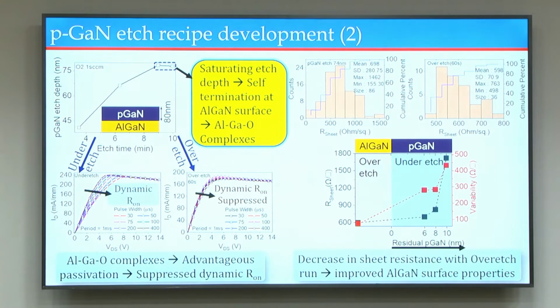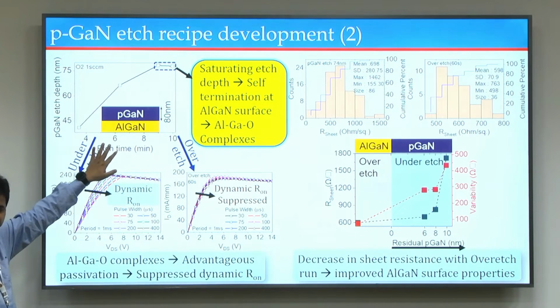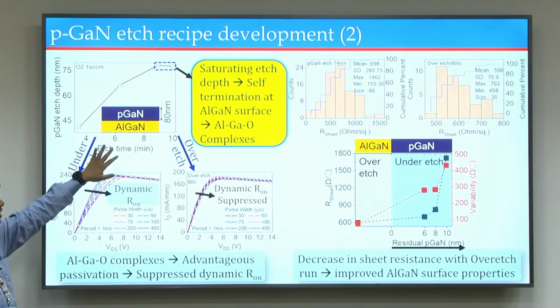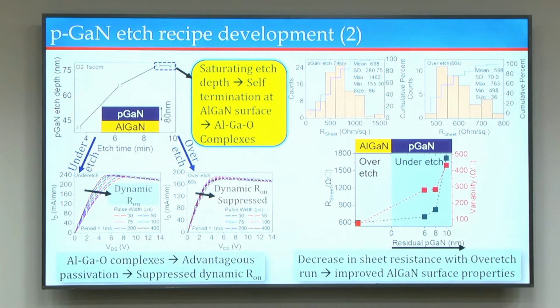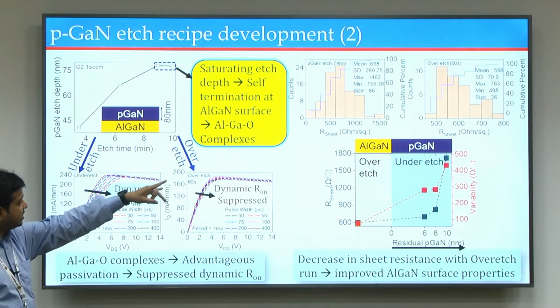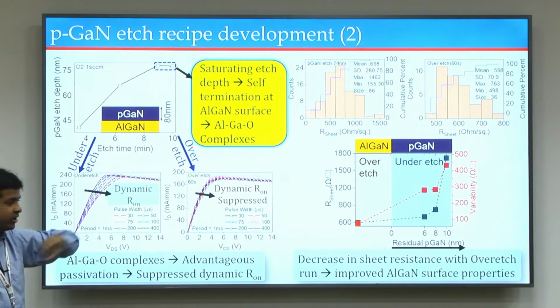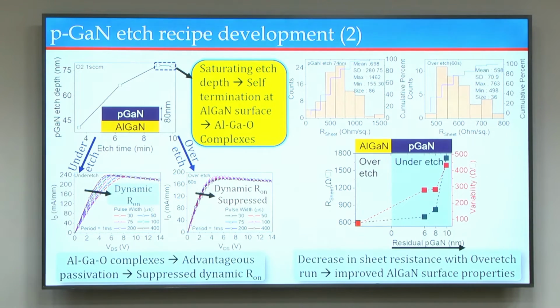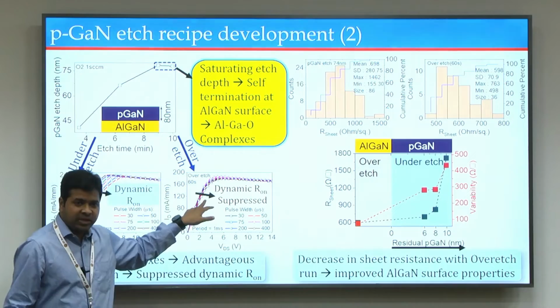So you need a chemistry like this, which I can tell you required a lot of runs and optimizations to get to this point, and once you have that, then you can completely remove pGaN from wherever you don't want it without having any variability like issues. Now I was talking about if you don't optimize this well, you may end up having serious variability issues in terms of sheet resistance and contact resistance. And the other way is that you may under etch, right. Okay, let's not etch completely, let's under etch. But what we found is that if you under etch, which means you are leaving some pGaN out there, you have serious dynamic R-on kind of issues, whereas if you do a full etch, there is no dynamic R-on kind of issues.